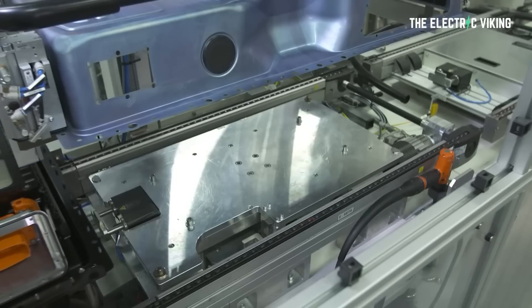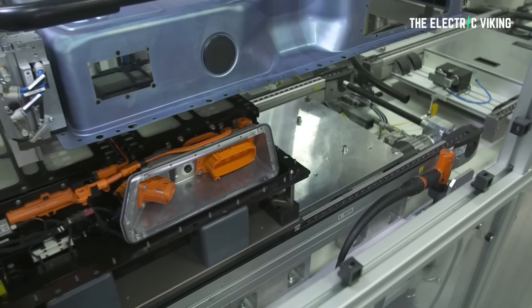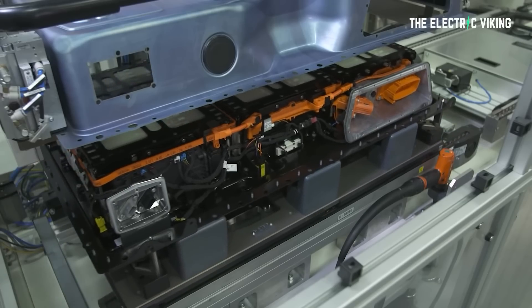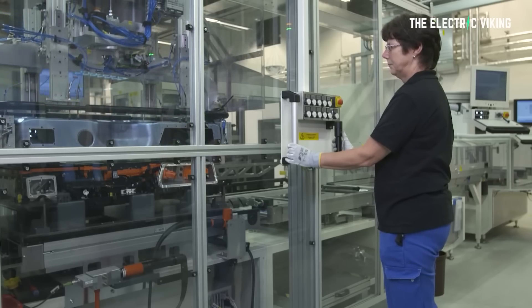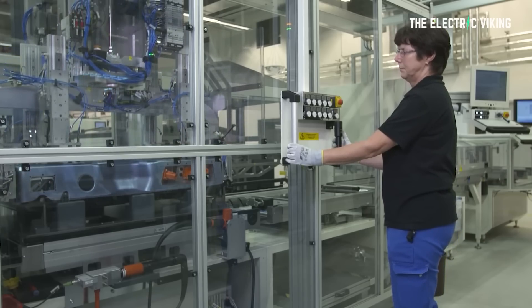The cell walls are much thicker in this battery, enabling it to become a structural battery, but that comes with a weight penalty. More steel is used to manufacture the battery, making it heavier — 10 to 15% is the approximate weight penalty from being structural. However, having a structural battery means Tesla can save weight on the car at a structural level, making energy density at the car level noticeably better — at least that's what Elon Musk is saying. There's still confusion because these numbers don't quite add up; we're still missing something.